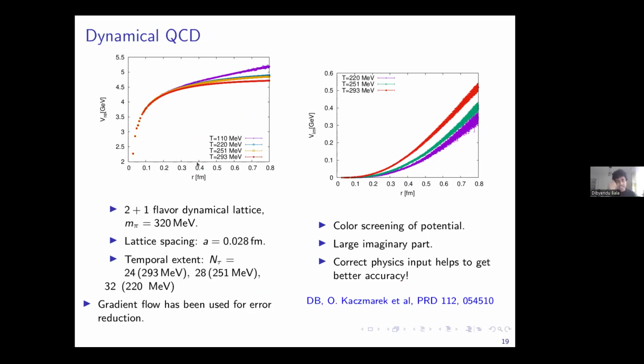Recently, this has been promoted to the full QCD calculation with dynamical fermions, and again we see this behavior that it's confined below Tc, and above Tc it shows screening behavior. And the imaginary part, as always, is increasing with both distance and temperature. I should mention that in the case of dynamical QCD, we cannot use the multi-level algorithm that we used for the quenched case, but we use something called gradient flow for this error reduction. Okay, but do you want to understand why at high temperatures the imaginary part rises very sharply?